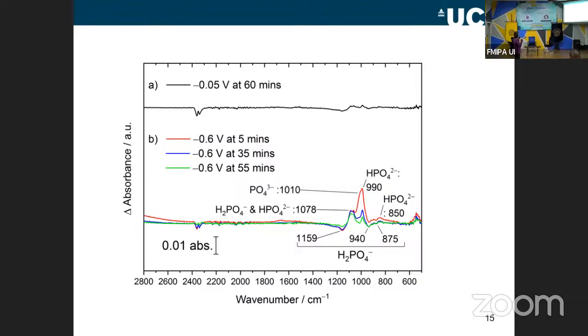So the top example, you can see we've applied a potential of minus 0.05 volts. This is where no reaction was taking place. And you can see it's relatively flat. There's a few small changes, but they're very small. And this means that there's no change in the species in that region. So there's been no reaction.